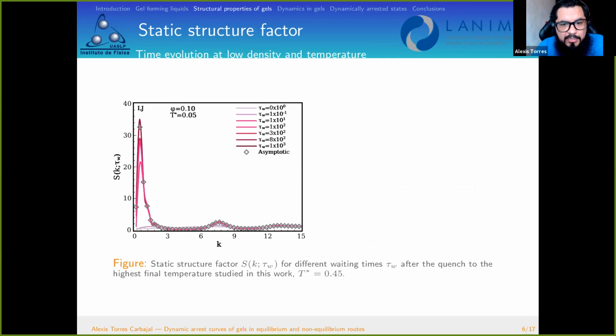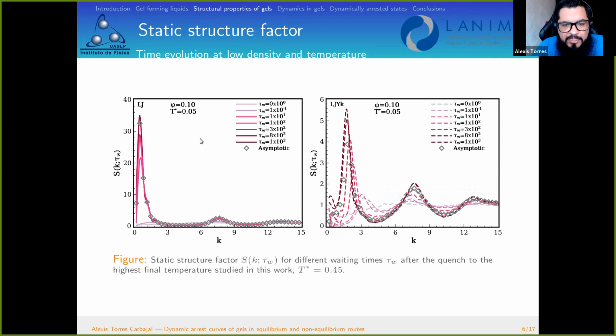It's well known that if the systems are quenched to a final temperature inside the binodal or spinodal region, the static structure factor exhibits a peak at low values of k, whose magnitude is finite in the sense that it stops increasing, and this is indicative that some kind of preferential length scale is seen in the system.